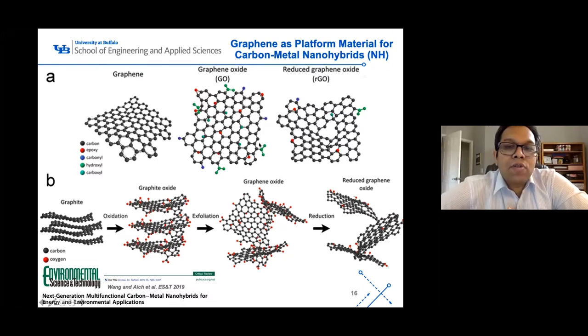developed that graphene could be made as graphene oxide instead of graphene, where you basically acid etch them and then functionalize them with different oxygen groups, oxide or carboxyl or hydroxyl groups, and then you get this high dispersibility, but at the same time you lose the electrical conductivity that graphene offers. Graphene is typically a zero band gap conductor, which is great, but we lose that conductivity.